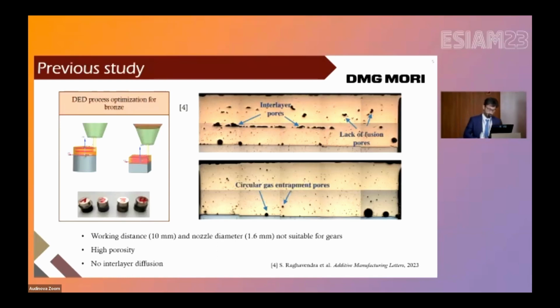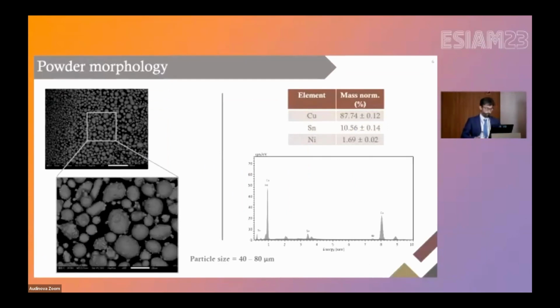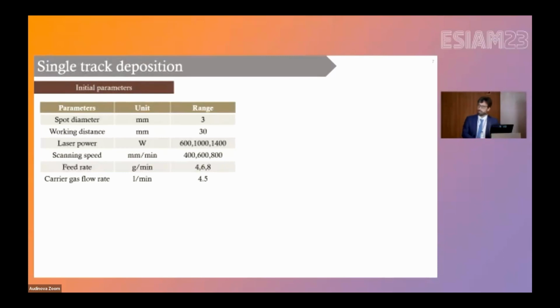So we decided to start this project from scratch. And we involved a private research center nearby Trento. ProM is the name. They operate at DMG Mori, but have the liberty of trying different process parameters. So we started with them to investigate this possible coating. Here you see the powder feedstock that we use for depositing bronze. We started analyzing possible combinations of process parameters to identify the process windows. In particular, as you can see here, we decided to increase the nozzle diameter and enable a larger working distance compatible with the deposition on gears.